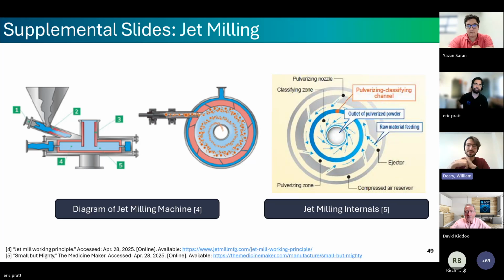The most effective milling that we found was actually the cryo milling. It's essentially a shaker mill with a metal impeller in the center, and the whole thing gets dunked in liquid nitrogen. And that was fantastic for getting really fine XLPE. But obviously, cryo milling is not exactly scalable. So the jet milling was a fantastic scalable process to get pretty repeatably fine particles that we could then sieve out and use a lower cutoff limit for the particle size.